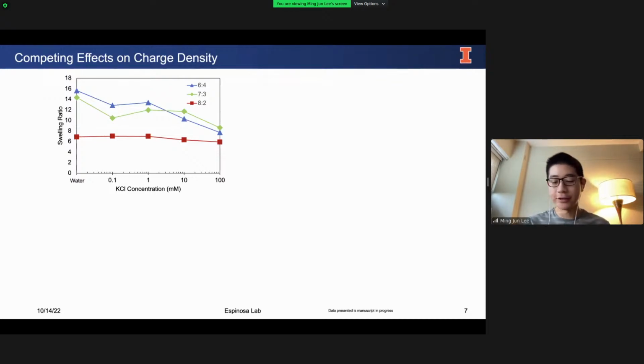Now I'd like to talk about the charge screening effects. The first figure I'm showing is the swelling ratio against potassium chloride salt concentration. Swelling ratio is taking the weight of a wet hydrogel divided by its dry weight when all the water has been removed. So this is a measure that tells us how much the hydrogel is swollen, in terms of volume.